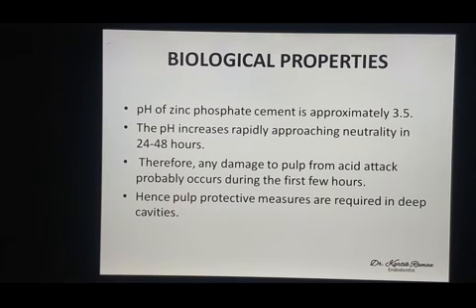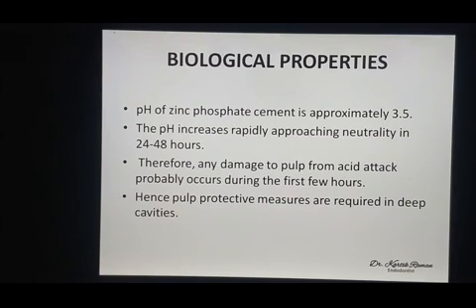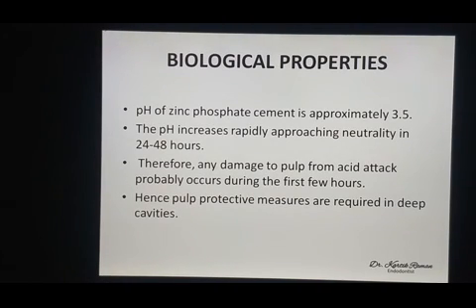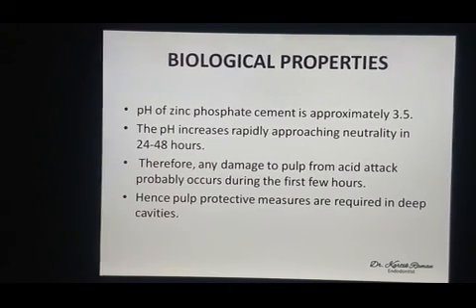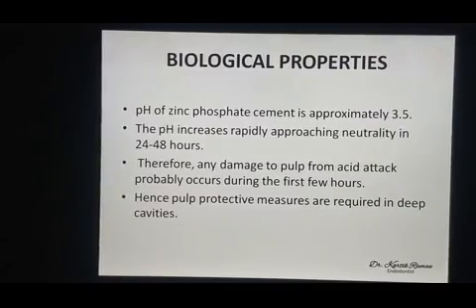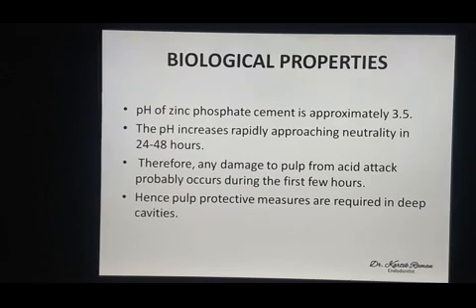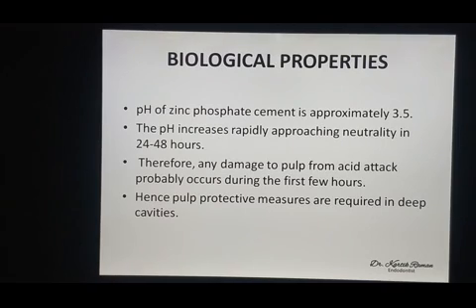Biological properties, as I had mentioned before, zinc phosphate is an extremely acidic cement. So the initial pH is around 4.2, and in a day's time it reaches approximately 6. So it's very, very acidic. So again, I'd like to reiterate that varnishes are used to cover all the walls and the pulpal floor of the cavity, and then zinc phosphate is applied. The pH slowly increases and it approaches neutrality in not 24 hours but approximately 48 hours. So we have to prevent the pulp from any acid attack in the first few hours.